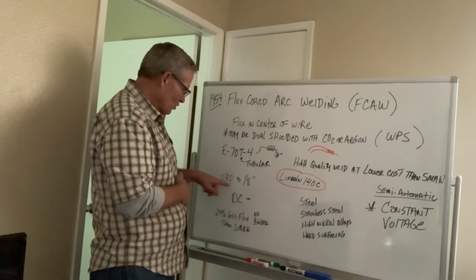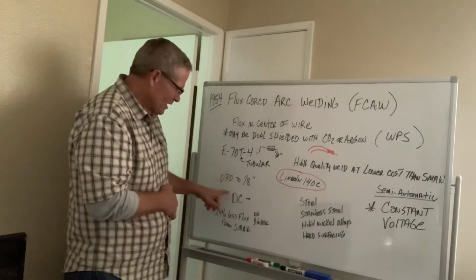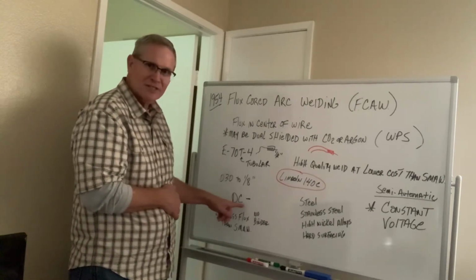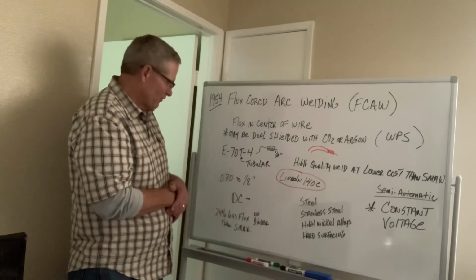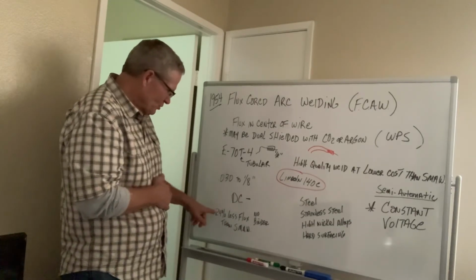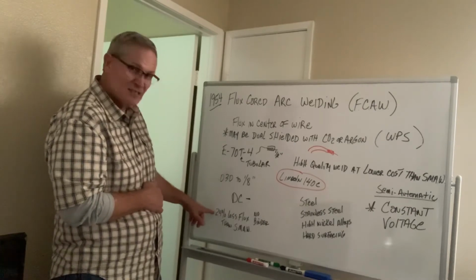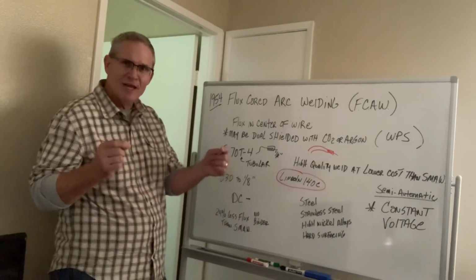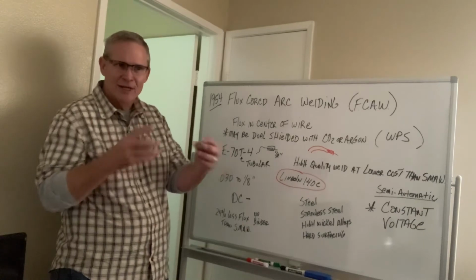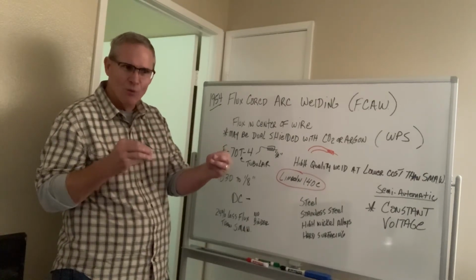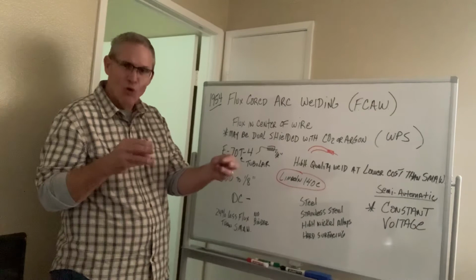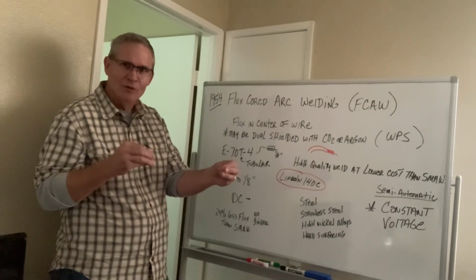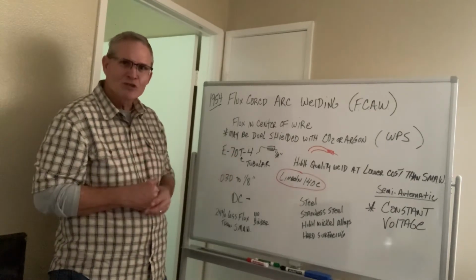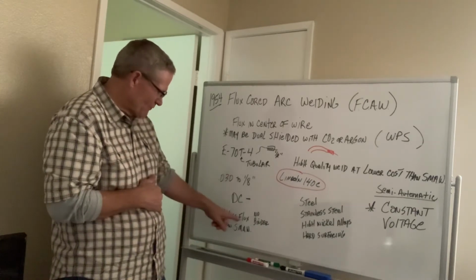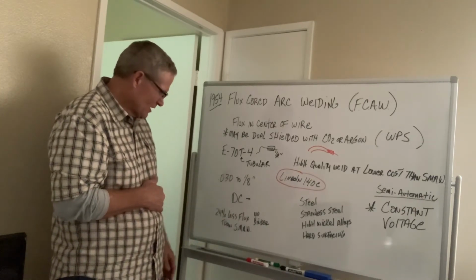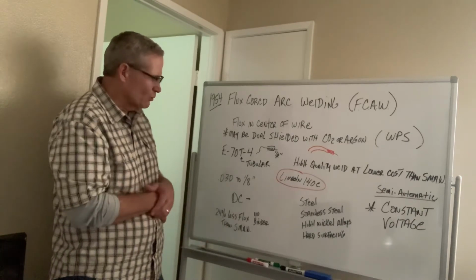So the wires are .030 to 1/8 inch in diameter. For this process we use DC minus polarity for the flux core arc welding. With this you use 24% less flux. On your typical 7018 electrode, it's got a binder in it to hold the flux onto the bare wire, if you will. But to hold the flux onto the electrode, it uses a binder. And there's no binders needed. So you end up using 24% less flux than you would with shielded metal arc welding.